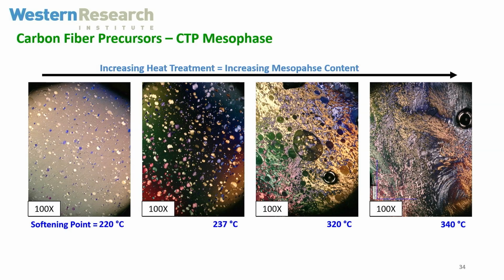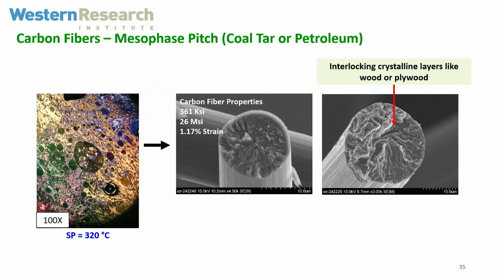And then on the bottom, these are the softening points. Typically you melt spin to make a carbon fiber with pitch, and you melt spin at around 300 degrees C. So these are liquid crystalline phases, but at very high temperatures.